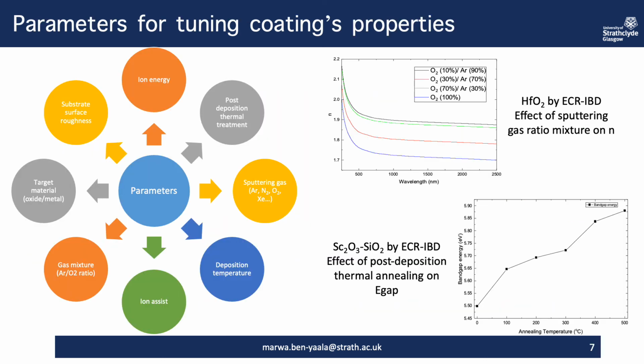So in this slide here, I'm presenting the deposition parameters that we are varying in order to tune some coatings properties. These parameters include the deposition temperature, the annealing temperature, and sputtering gases. We are using argon, nitrogen, oxygen, and are planning to use xenon, and also playing with the gas mixture, so the ratio between argon and oxygen.